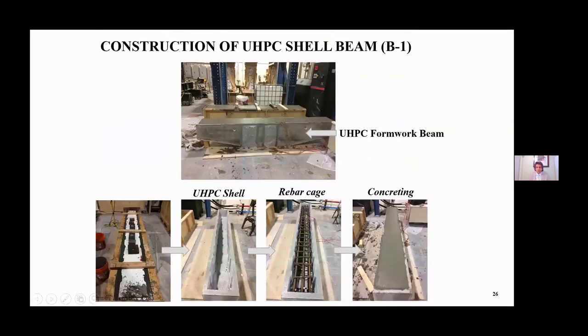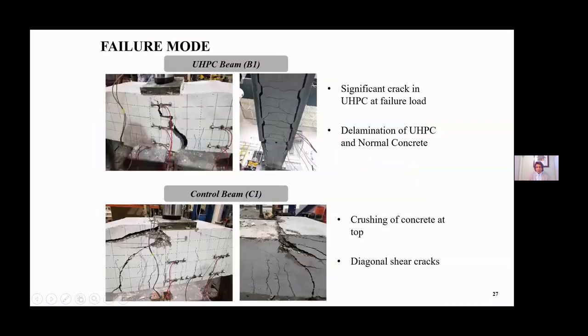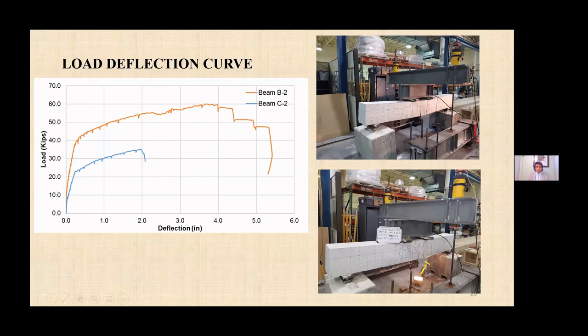And these are some of the elements that we have tested. I don't have the time to go over the details of how you need to make sure that the material you fill this shell with acts compositely with the UHPC shell. You got to be careful, okay? And if you do that, this is a same size T-beam using a normal strength concrete. This one is a UHPC shell with the normal strength concrete, both same cross-section area. And you can see how much that little bit of UHPC increases the strength. So this is another concept using a UHPC. So your formwork is made of the UHPC, basically.